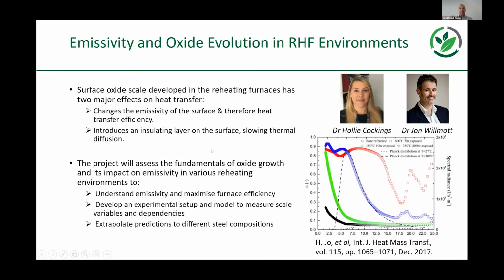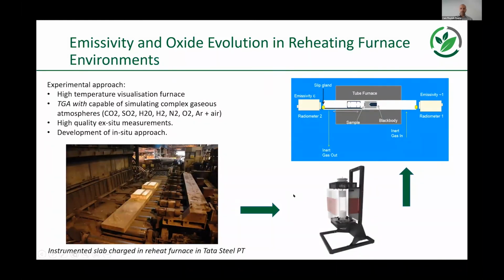So if we have to heat our materials over 1,000 degrees and harness this useful phase transformation, then at those temperatures, the emissivity becomes incredibly important in determining the heat transfer efficiency. And what we've seen in the past is that different levels of oxidation can give you different emissivities and therefore different efficiency of getting the heat into the material. So what Hollie at Swansea and Jon at Sheffield are working on is being able to link those two activities together so that we can understand more about the relationship between the emissivity and the oxidation, and then be able to optimize the heat input into the material.